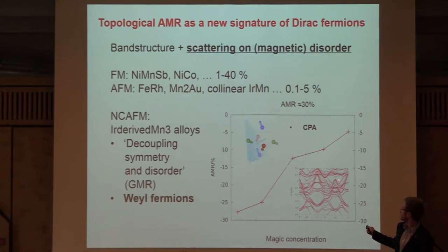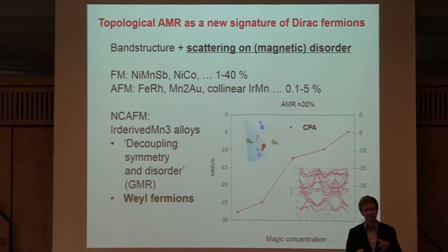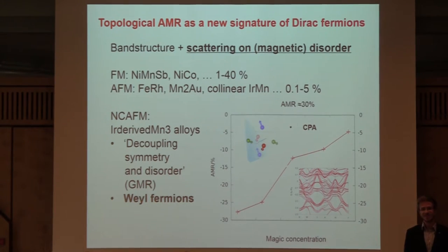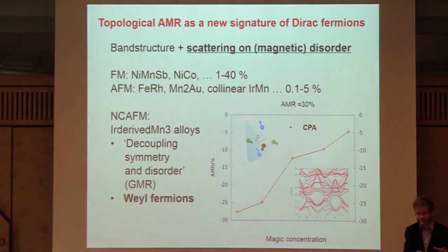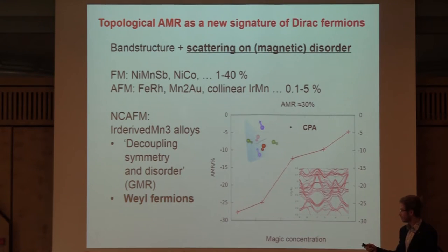So the point is that you will arrive with some Weyl points close to the Fermi level, and this leads potentially to large values. So this means that actually the gap which remained from the 90s in the understanding of anisotropic magnetoresistance, since there were just some models from Campbell, Fert, and Jaoul, which could be applied just for certain cases of materials, we can extend it by this, and now today we can understand even on a quantitative level this ancient spin orbitronics effect from the 19th century.